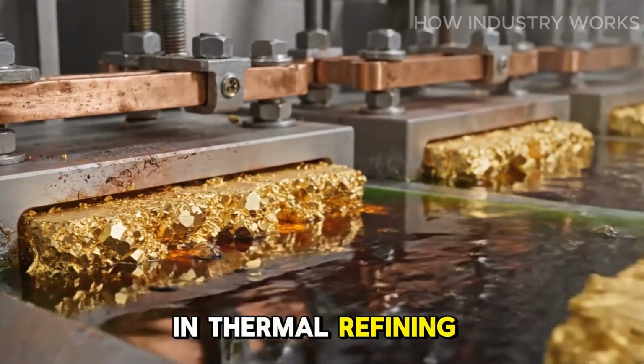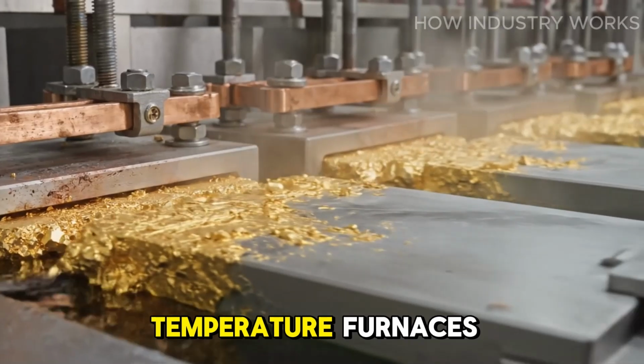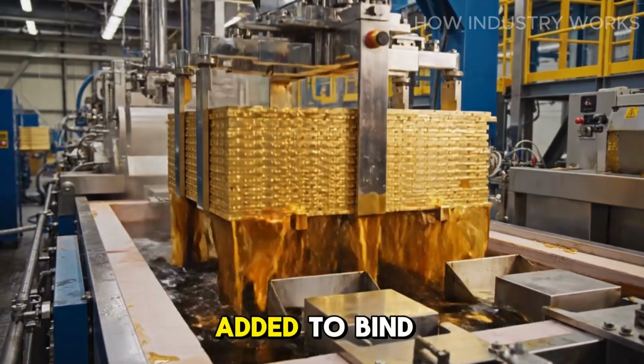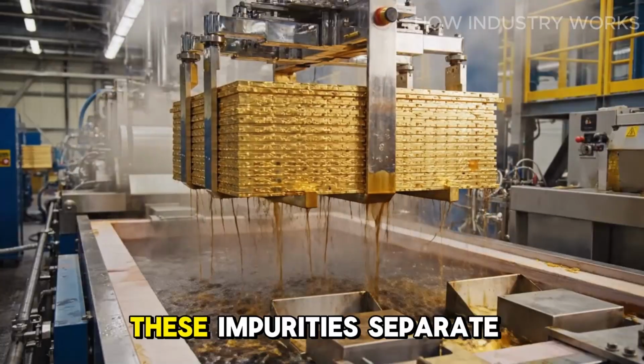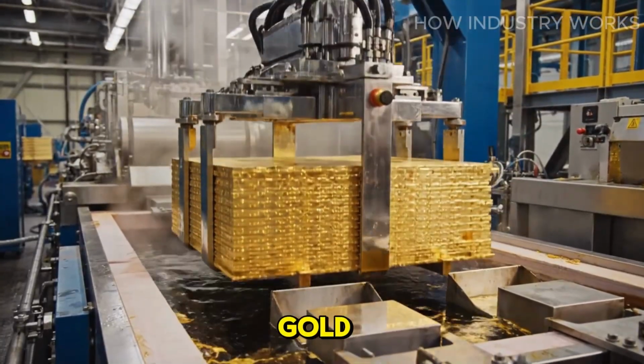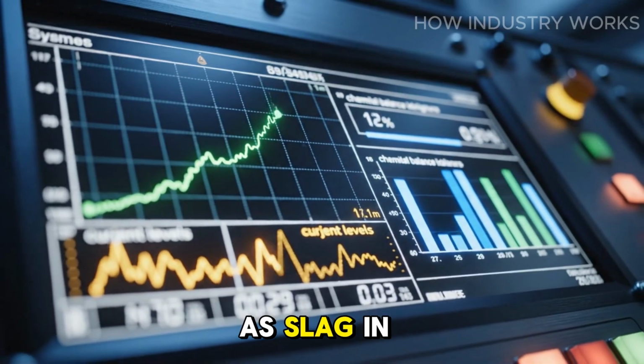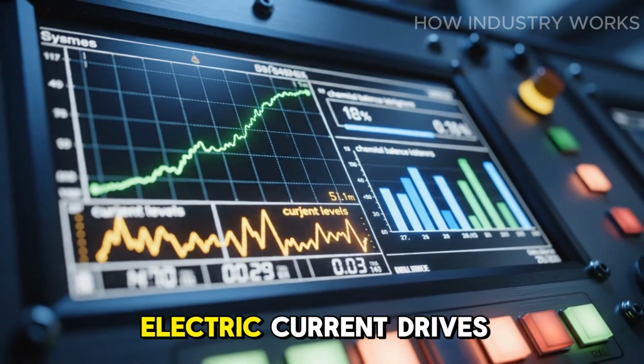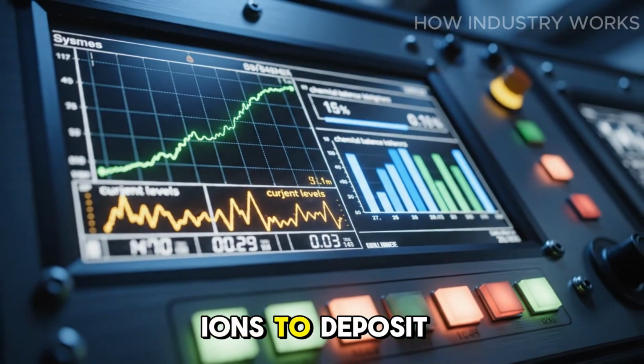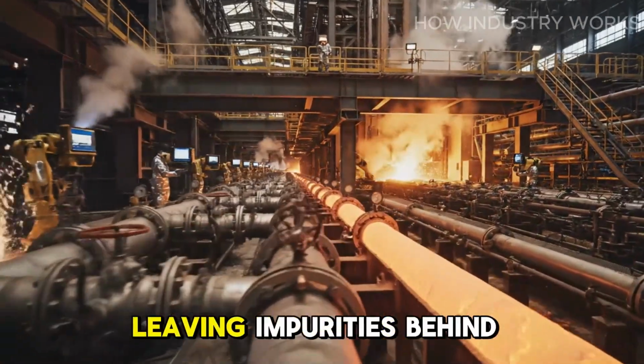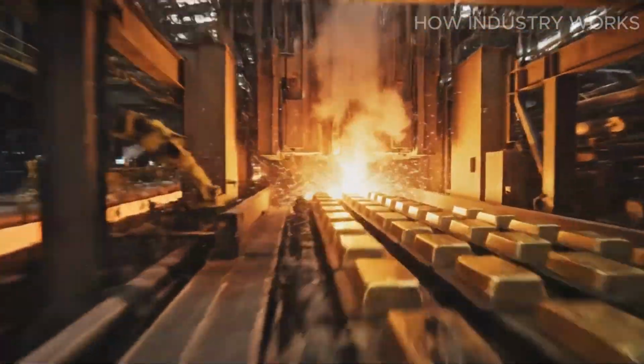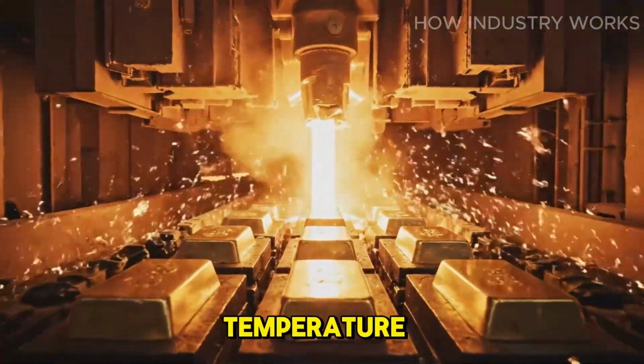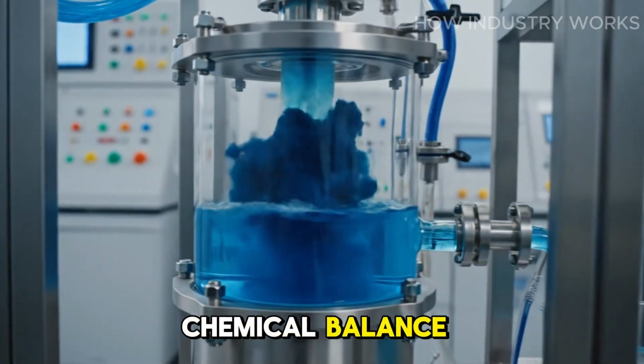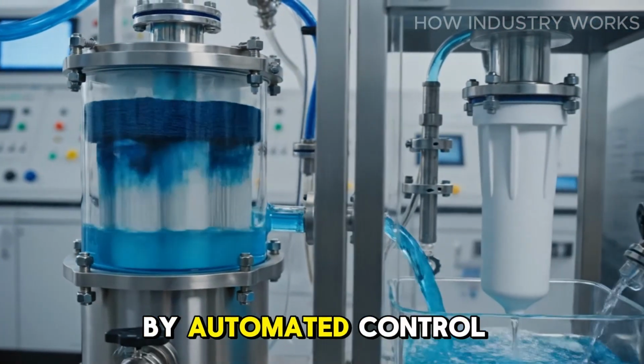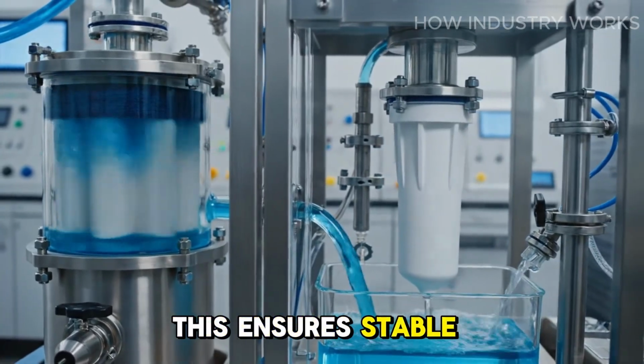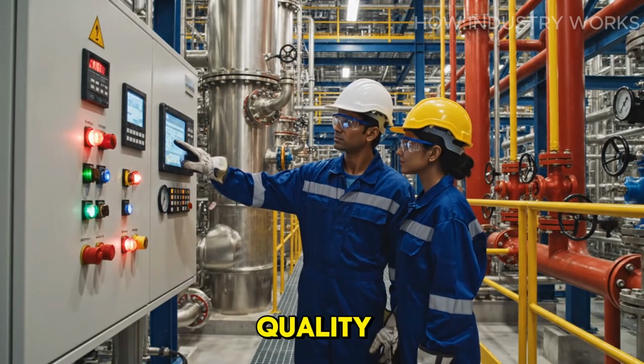In thermal refining, the material is heated in high-temperature furnaces where fluxes are added to bind unwanted metals. These impurities separate from the molten gold and are removed as slag. In electro-refining systems, electric current drives gold ions to deposit onto cathodes, leaving impurities behind in solution. Throughout the operation, temperature, electrical current, and chemical balance are continuously monitored by automated control systems. This ensures stable conditions and consistent metal quality.